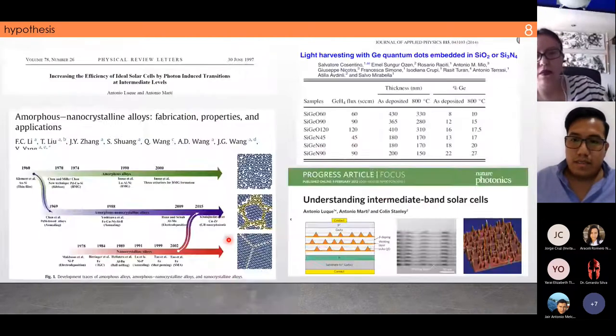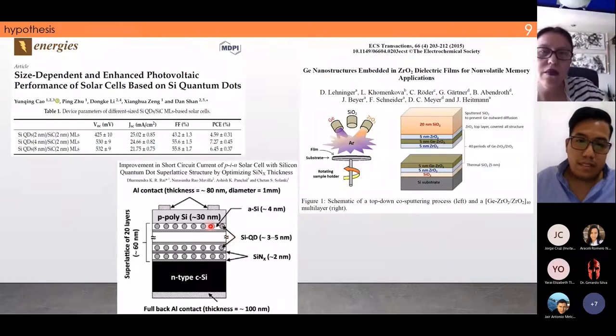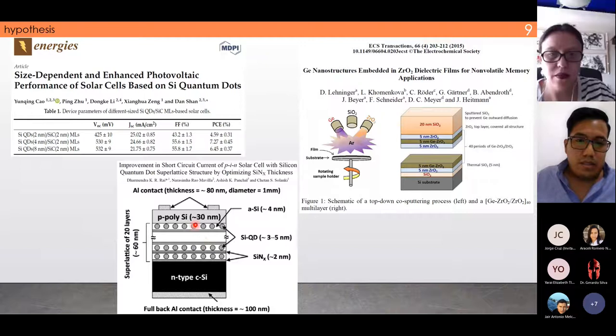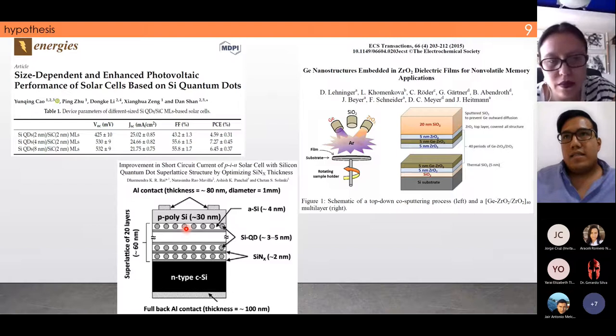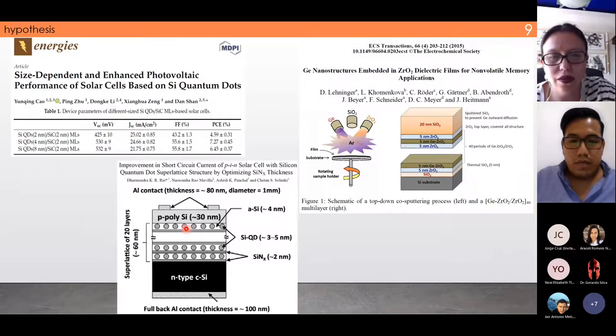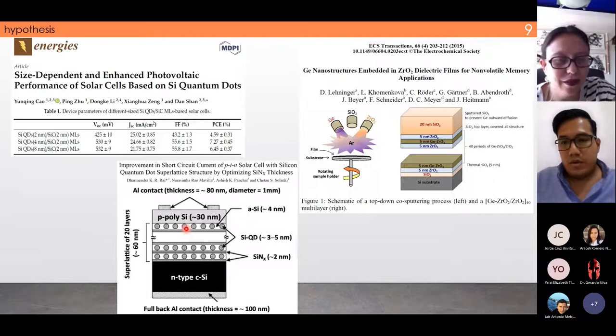So this is another advantage: one process, less temperature, and just one layer. Another is the quantum dot size. This is very important, because the band gap of the material depends on the size. To obtain these quantum dots, you use a higher temperature in the case of silicon. And with germanium, we obtained this cluster with less temperature because we use hydrogen flux in the annealing stage, because this hydrogen reduces the germanium oxide. So for this reason, we obtained lower temperature.